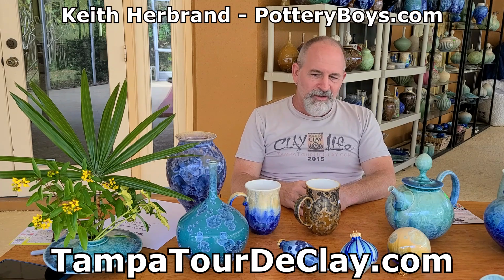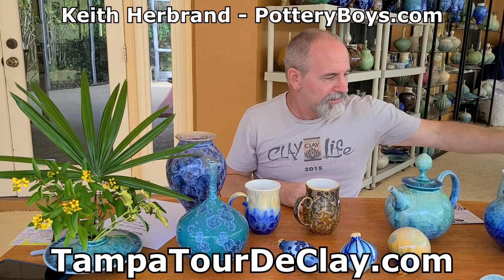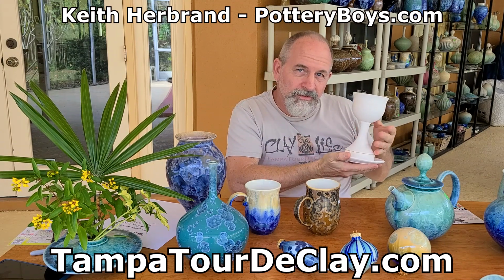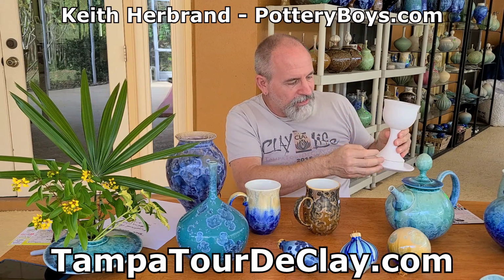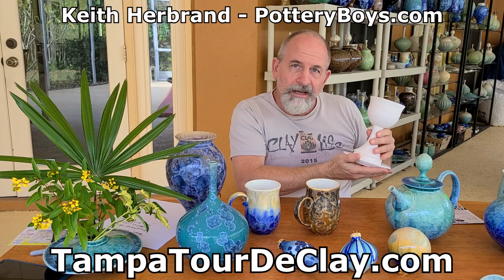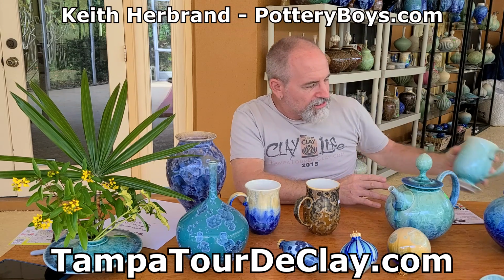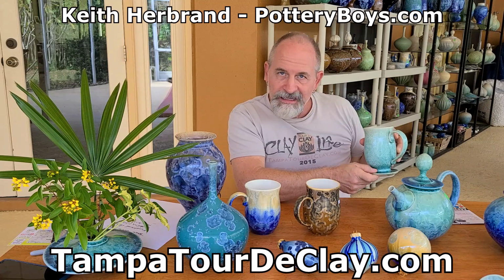One of the things about the crystalline glaze that makes it unique and challenging is that it's a very runny glaze. So when we throw a vertical piece, each piece has to have a catch tray that's thrown to fit exactly to the bottom of the piece. Then we glaze the piece, and a good share of the glaze flows down and is in this catch tray. After it is finished and cooled, we break this bottom off, grind it and polish it so it's a nice finished piece. And this is just a mug that's been glazed. We haven't broken the bottom off yet, but you can see there's a lot of glaze there.